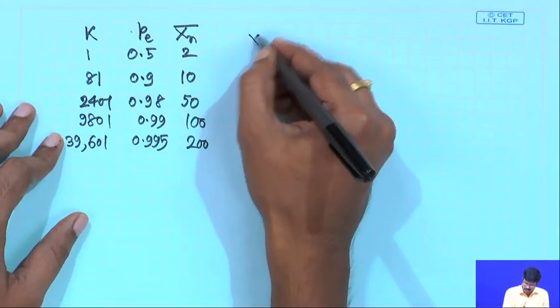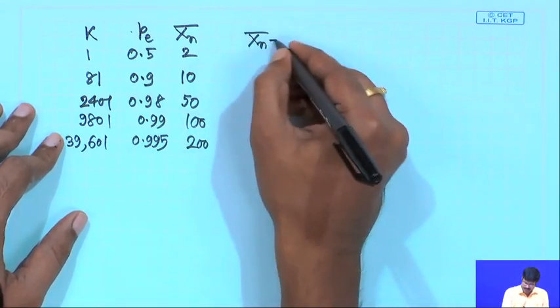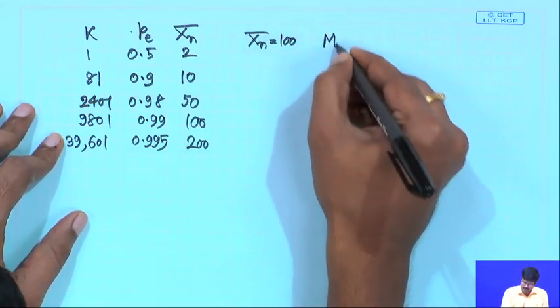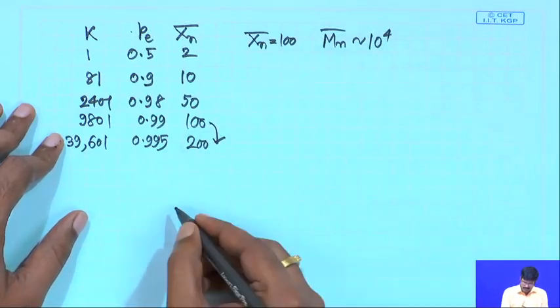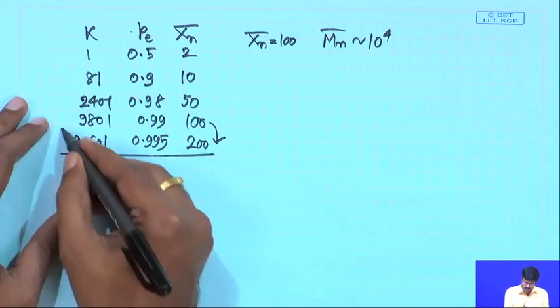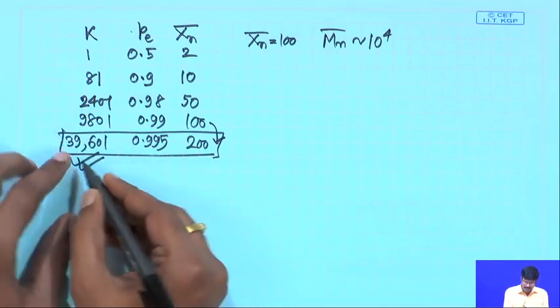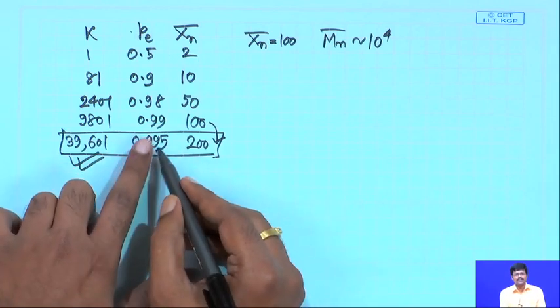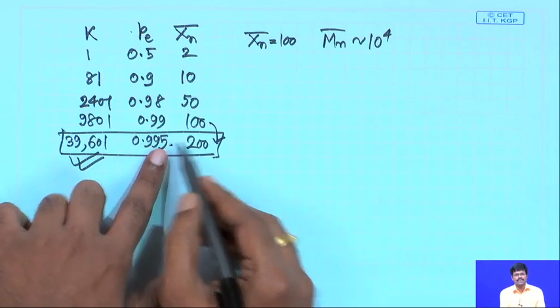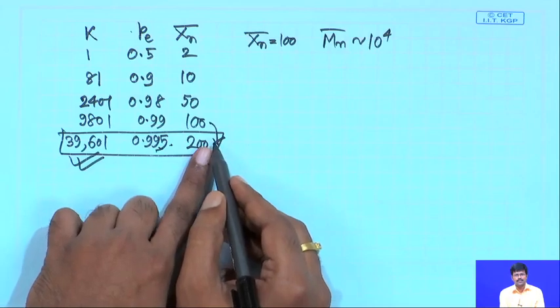Now, as I told, in general for your typical step polymers, when xn bar is 100, your molecular weight becomes around 10 to the power 4. So, you have to go beyond that. So, you need this kind of situation. So, your equilibrium constant has to be as high as this in order to get this kind of reaction, extent of reaction will be then 99.5% and your Xn bar will be 200, reasonable maybe.